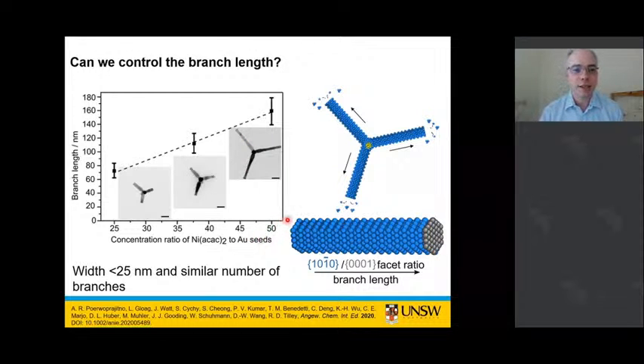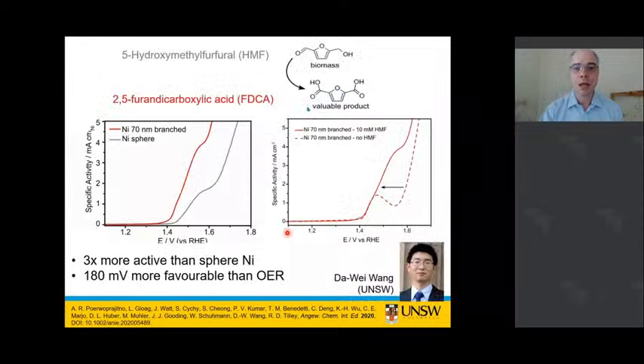And this was interesting from a catalytic perspective, because for this surface facet along the sides, we did some DFT calculations with one of my colleagues, Priyank, and his calculation showed that these facets along the side should be more active in terms of our HMF oxidation, our biomass oxidation, than these end surface facets. So we felt that if we had longer arms with more of these exposed facets on the side, then we should have better catalysts. And that was indeed the case.